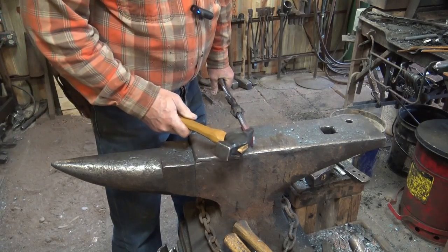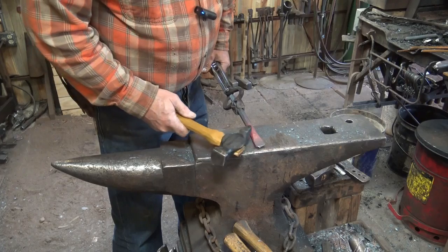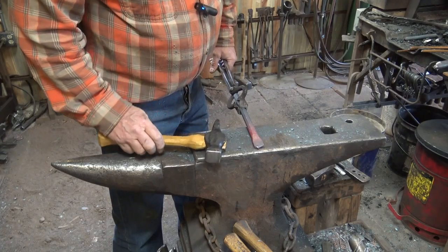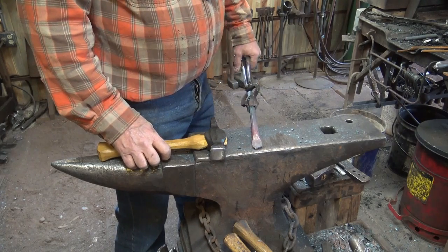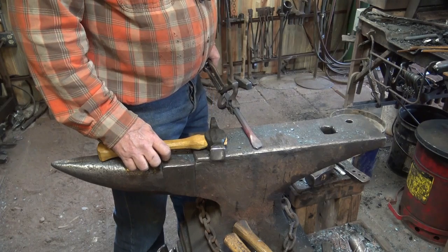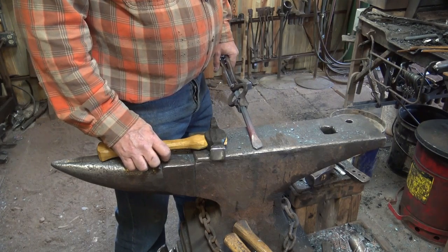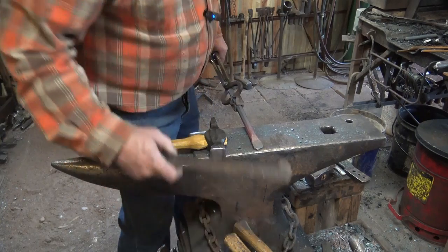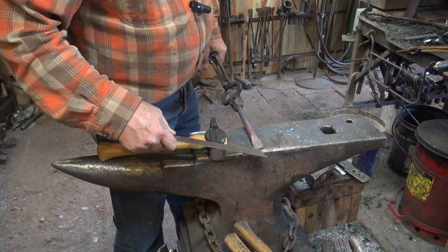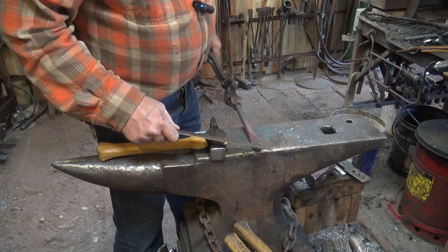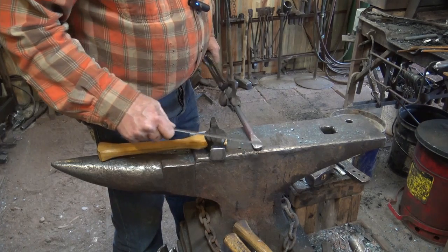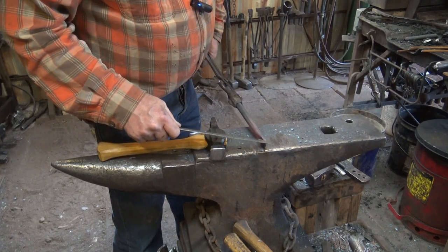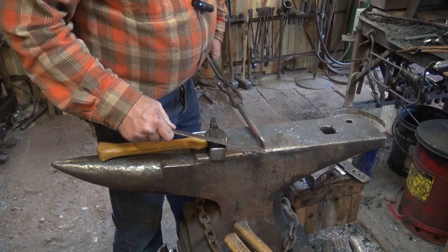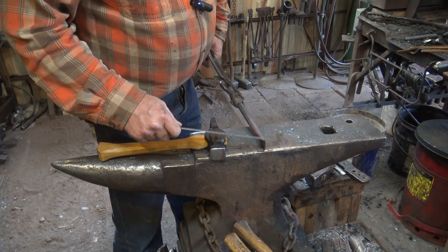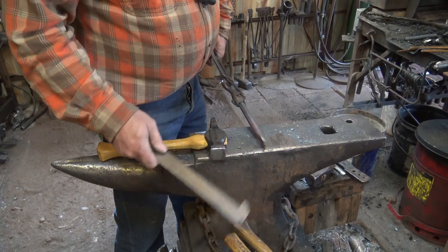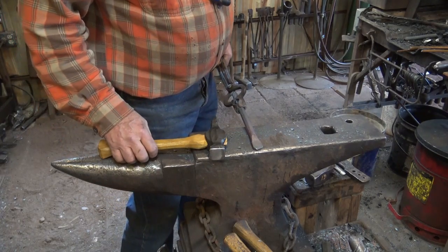Now then, this is actually about an eighth of an inch thick right now, and probably about an inch wide. If you wanted a slot punch, like when we were slot punching the bottle opener, that's pretty much where you would stop. Later you'd come back and grind this straight across and round up these corners so that you have a nice round transition on your punched hole. But it's really just that simple. The slot punch and the chisel are about the same thing at this stage.